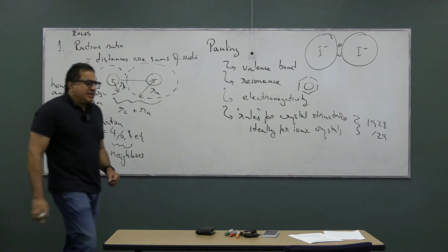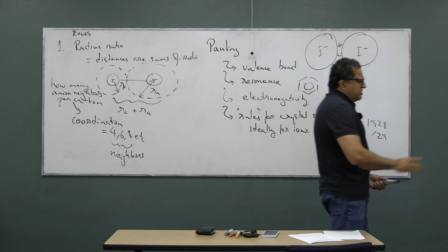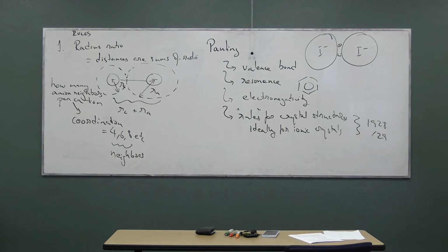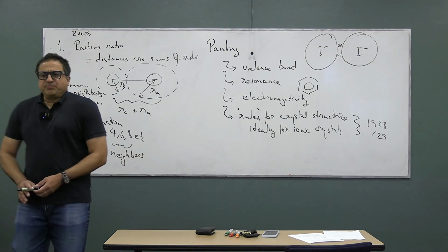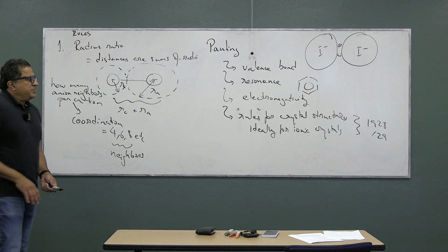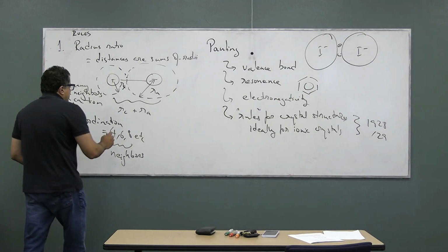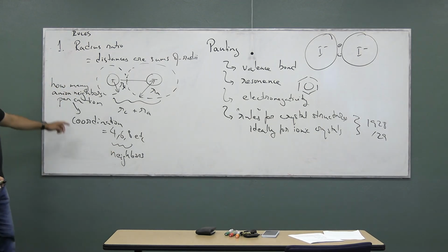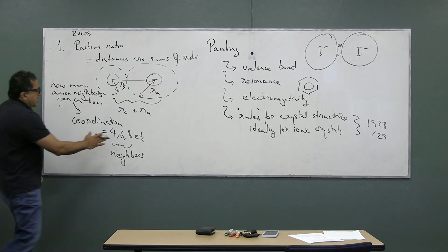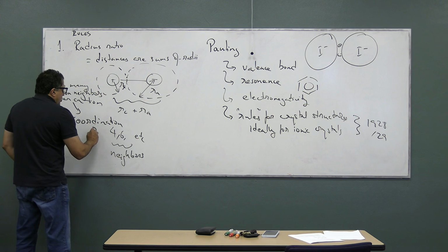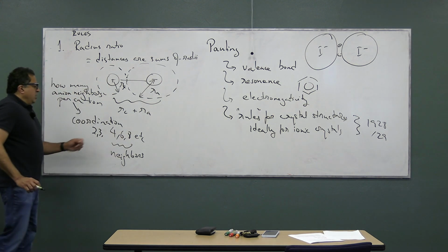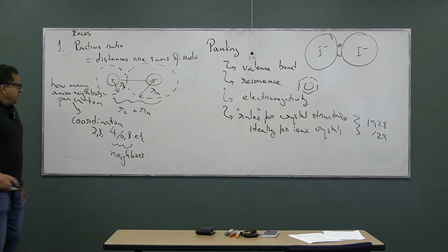And when we've looked at elemental structures, we've been talking about the coordination number. Simple cubic is 6, body-centered cubic is 8, face-centered cubic is 12. So this is an important consideration. The mechanical properties change, the density changes, a lot of things change depending on the coordination number, and certainly the electronic properties. The coordination number can even be 2, 3, 4, 6, 8, etc. The coordination number depends on the radius ratio.